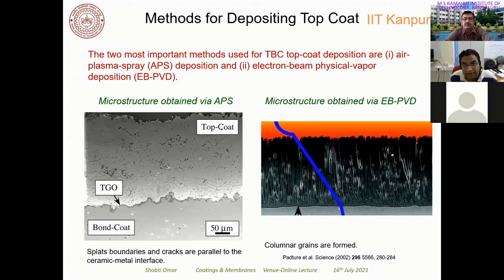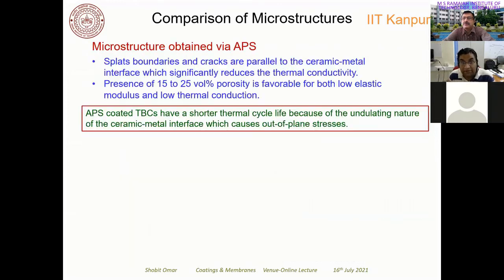And you can see in the microstructure prepared from the air plasma technique that the splats that are formed have cracks or porosity along the interface of the bond coat and this top coat, right? However, in the microstructure that you obtain from EBPVD, the grains are columnar in nature. Right? So these are two important features which you will observe in the microstructure. Now, what happens is that when the splat boundaries and cracks are parallel to the ceramic-metal interface, they reduce the thermal conductivity, and that is very good. Right? And that will protect your component material.